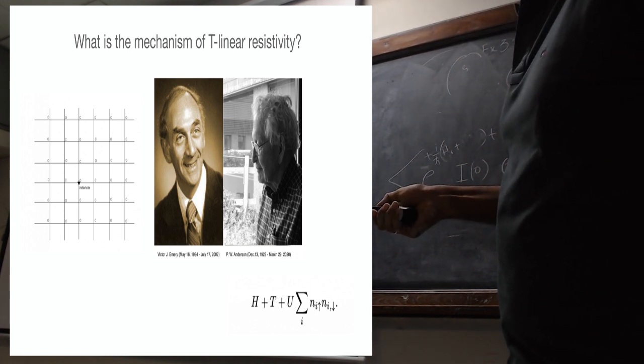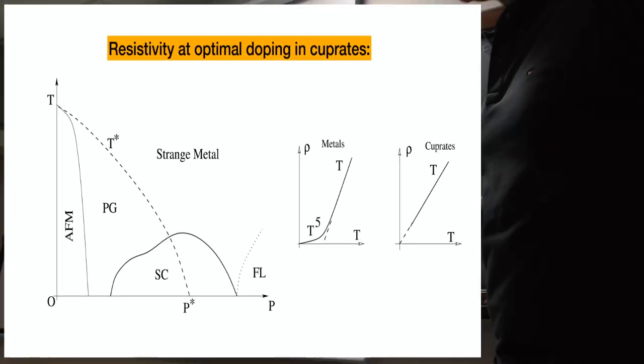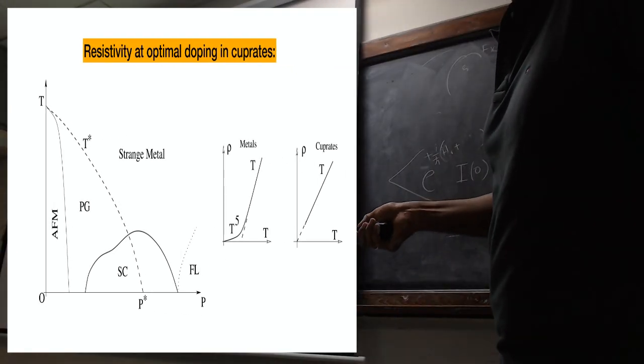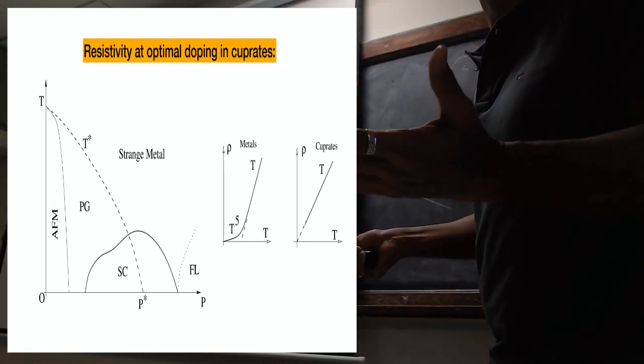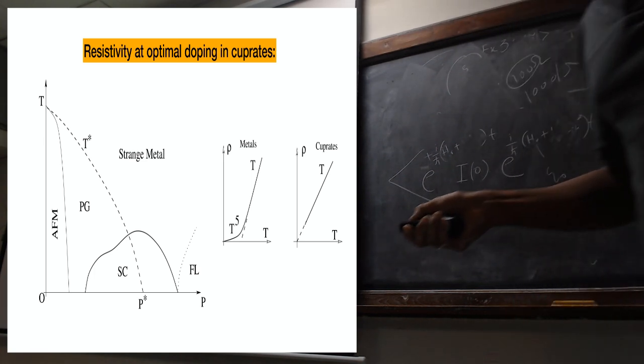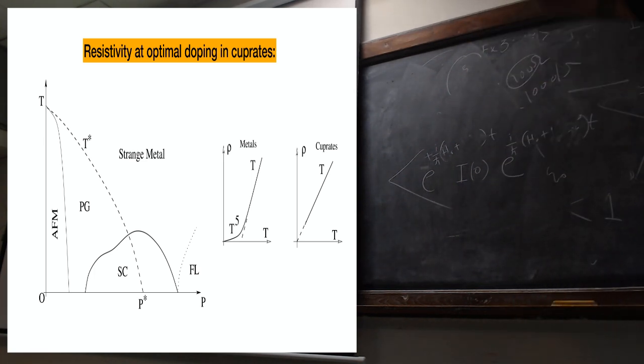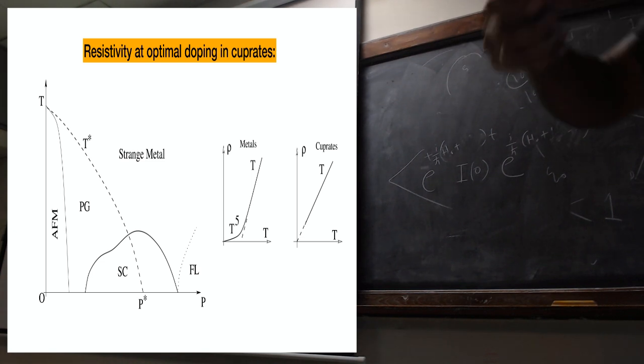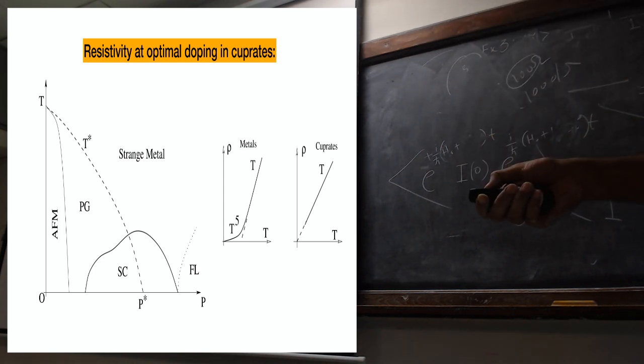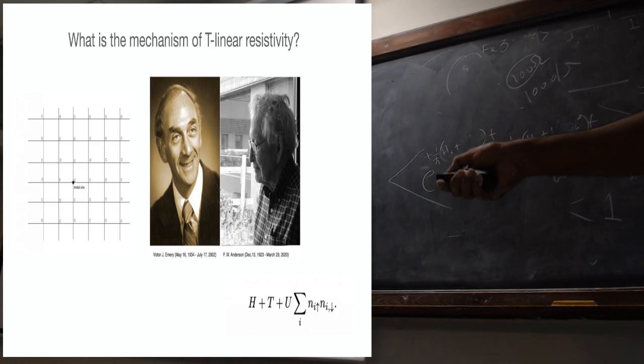He argued that when you dope the material, doping creates holes which are mobile on the oxygen sublattice. The copper spins stay, because copper spins are antiferromagnetically correlated. Once the holes are there in the oxygen sublattice, this antiferromagnetism weakens because the superexchange weakens. There are spin fluctuations on the copper sublattice, but the mobile carriers are on the oxygen sublattice. So if you look at this, there is a copper, oxygen, copper, oxygen, copper, oxygen.